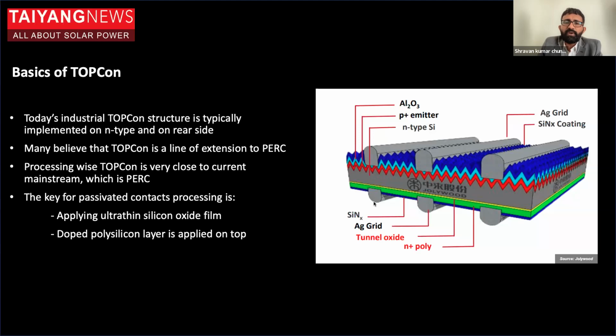Okay, so here is the basic structure of the TOPCon. So today's industrial TOPCon is implemented on N-type on the rear side. So that means a stack of a tunneling oxide and doped polysilicon are added onto the rear of the typical PERC cell. So many believe that the TOPCon is in line of extension to PERC. That's because it is very close to the current mainstream, which is PERC in terms of manufacturing. So the crux of the process are applying a ultra thin silicon oxide film and a doped polysilicon layer on top of it.